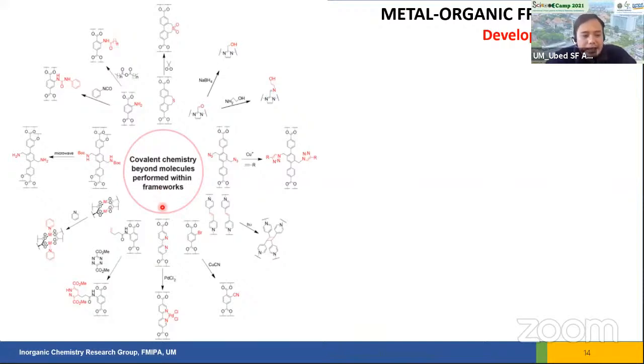I will give you some examples. For example, here, metal organic frameworks that use bipyridine dicarboxylate, there are two nitrogens in between. From inorganic chemistry, we can directly use this type of moiety as the organic ligand for certain metals. For example, we can react this MOF with palladium chloride, resulting in metal organic frameworks with palladium chloride inside the